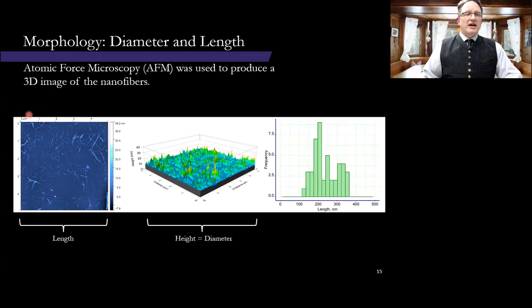If you look at this left image, this is a two-dimensional XY plane that is generated in data. From here, we can derive and generate the length data. In the three-dimensional, the AFM gives us a height number here, and that height is equivalent to our diameters in our fibers. From that, we can generate a frequency plot of fibers for that particular sample.